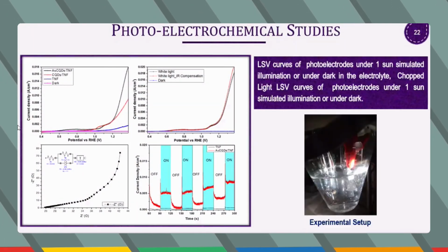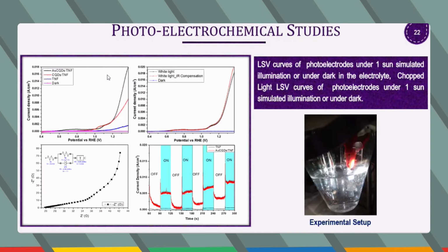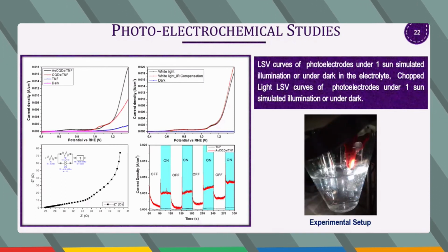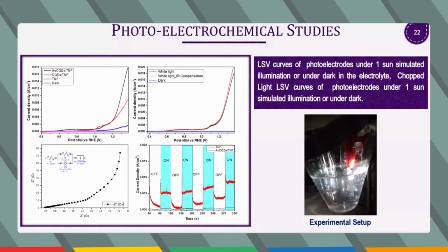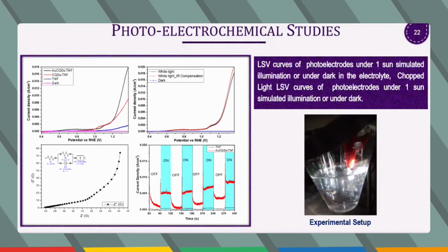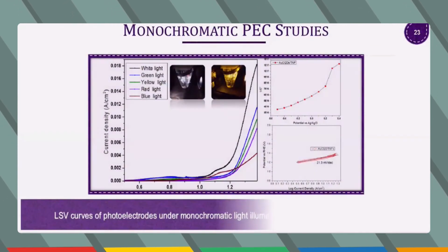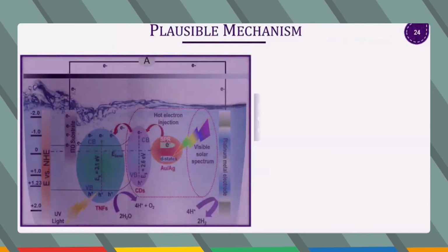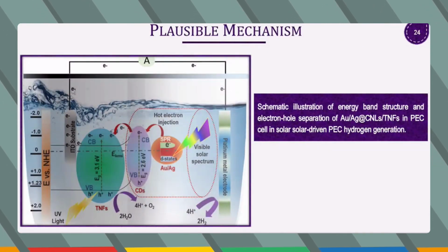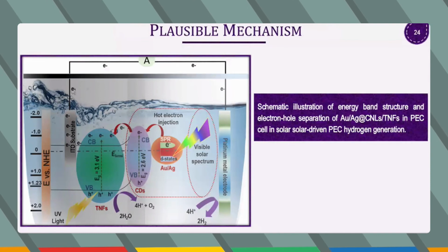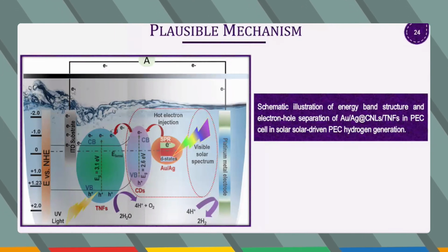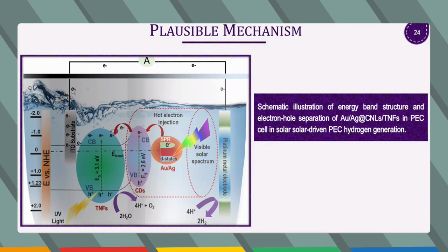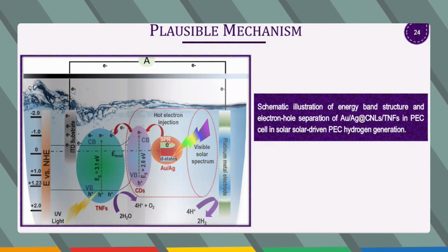And these are the PEC results for these electrodes. As we can compare the electrodes with the pristine carbon quantum dots, with these we observed high current density and also a higher water splitting rate, which resulted in a huge amount of hydrogen produced after the reaction. The IPCE studies were also conducted for this material. This is the plausible mechanism, as I was stating earlier, by which this material is able to harvest more light, and it actually acts as an artificial leaf which can harvest more solar light and be used to split water.